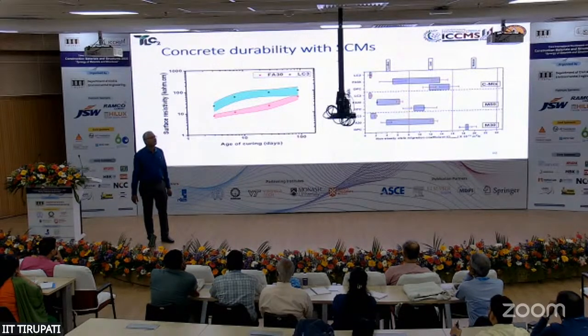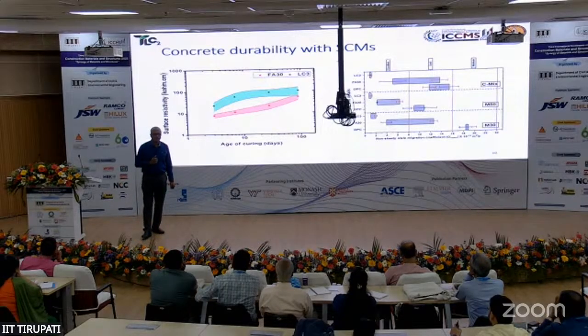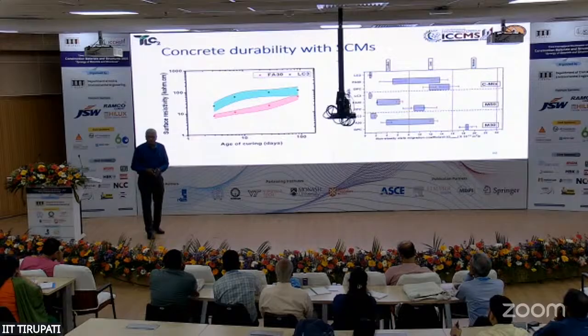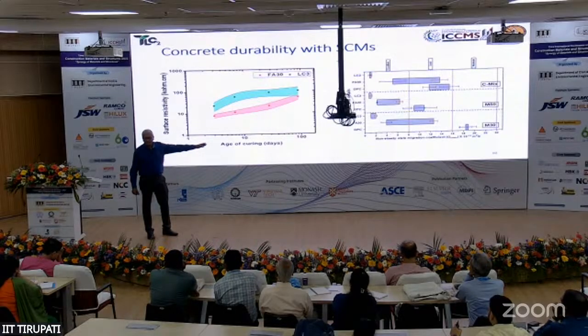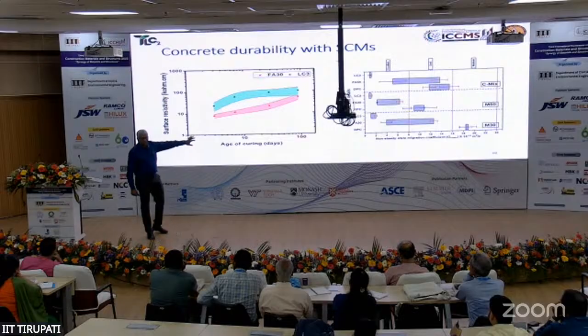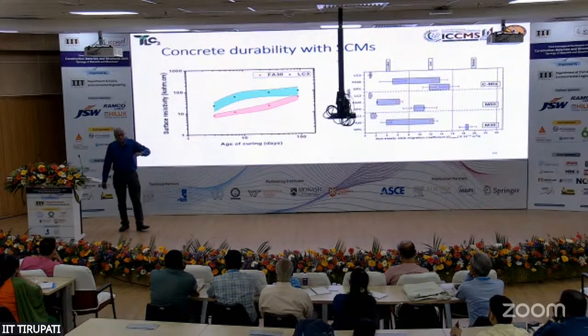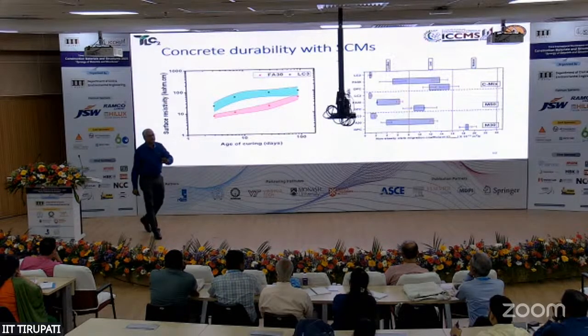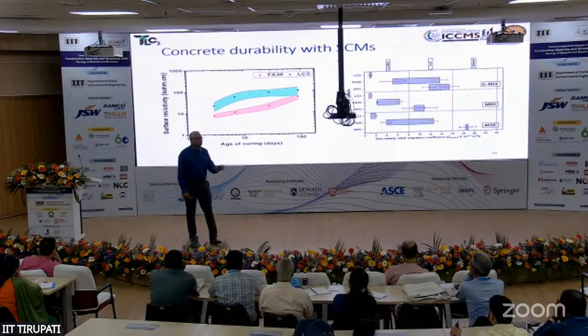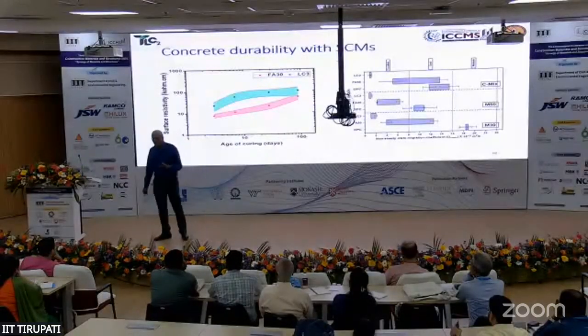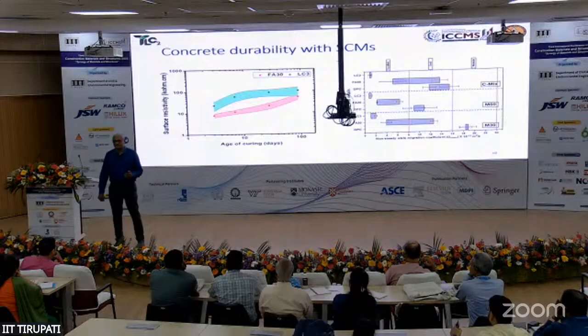For instance, in the Mumbai Trans-Harbour Tunnel, that was the limit specified for the bridge and tunnel elements. So you can imagine that level of durability. That was a 65, 70 grade concrete. But here, this is a 30 MPa grade concrete, and you're able to get still a very high level of durability. So this goes to show that when mineral additives are used, you have the potential to improve durability, especially in chloride environment, right, at lower levels of structural strength.